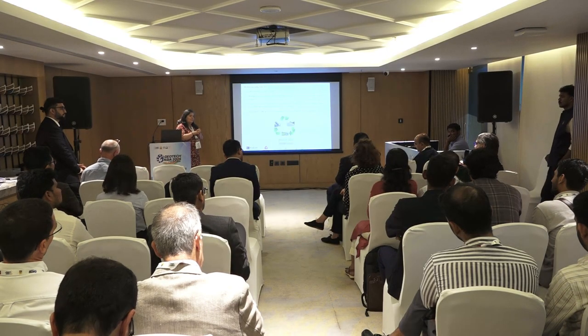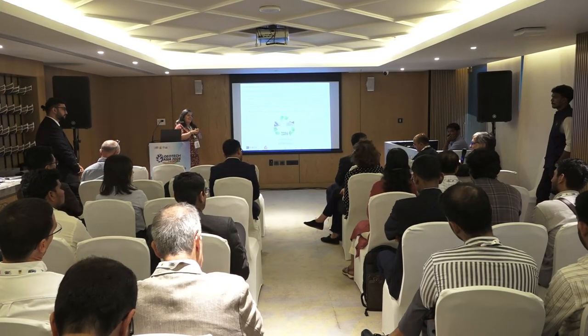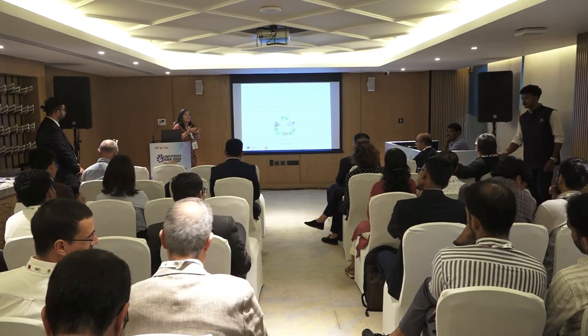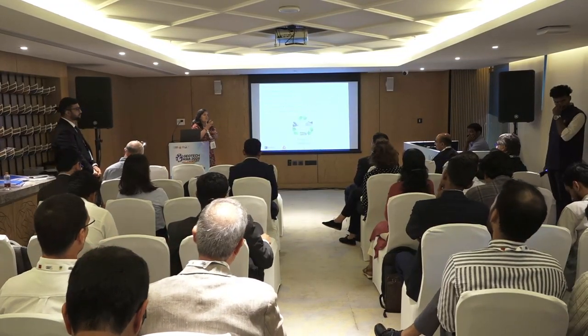So it would be interesting for you to look at whether there were different effects at those strain levels, because by the time the tensile strength is reached, your structures have failed and you're no longer interested whether it was soil or CDW. So it would be good to go back and look at what's happening at the lower strain levels. We checked it at 2%, but we noticed that at very small strains the material remains stiffer than the intact material, but doesn't fail at these values.